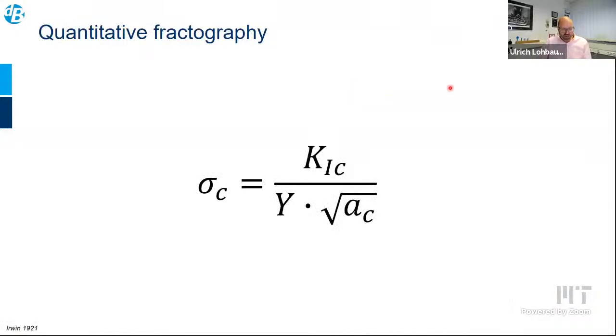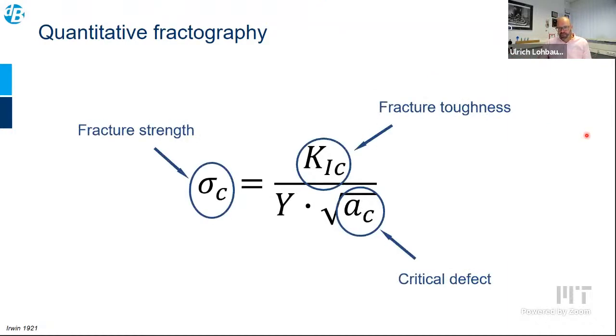You can use fractography in a quantitative way. Let's say you wish to know the level of stress that was necessary to fracture the component. So we go back to the very simple equation from Irwin, where he relates the fracture toughness with the critical defect and the fracture stress. In that way, as the defect is increasing, the strength is decreasing. And if you wish to increase the strength, then you need to decrease the defect size.